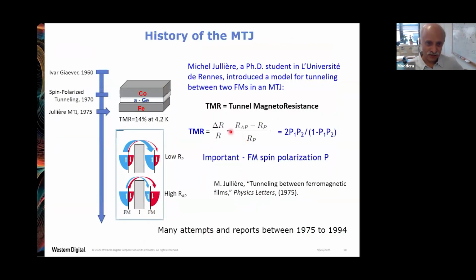So now we come to the magnetic tunnel junction. Based on what Meservey and Tedrow showed, that the spin is conserved in the tunneling process, and you can also have spin polarization coming from magnetic electrodes, Michel Julliere, who was a PhD student at the time in France, came up with this model. If you put two ferromagnets separated by a thin insulator, in his case he used amorphous germanium, which was not the best choice at the time, the tunnel magnetoresistance can be determined by changing the magnetization, changing the resistance of the system when you go from the parallel state to the anti-parallel state. That is what the TMR is about. This is proportional to the spin polarization. As you see here, P1 and P2 are the polarizations of this magnetic electrode and that magnetic electrode. Naturally, one expects to see a very large TMR depending on the value of P, which is very high.